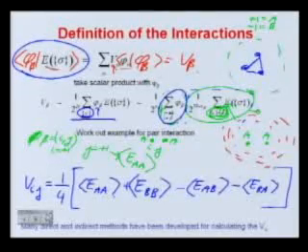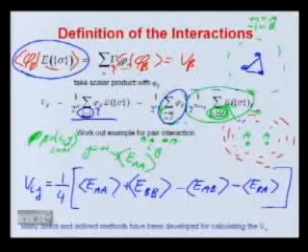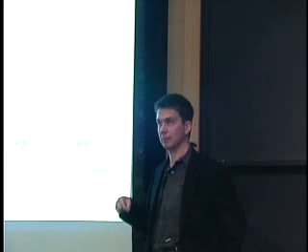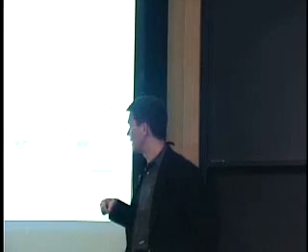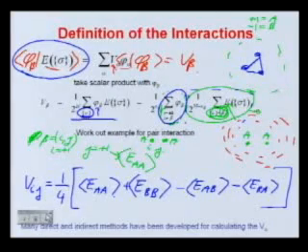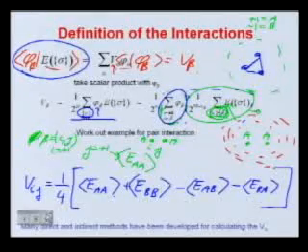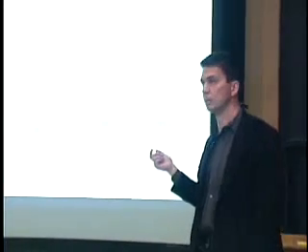This is the formal definition of the expansion coefficients. First of all, notice that they are not potentials. They are energies, and they are energies of configurations. So this is not the potential between the A atom at I and the A atom at J, because the configuration around it modifies that interaction substantially.